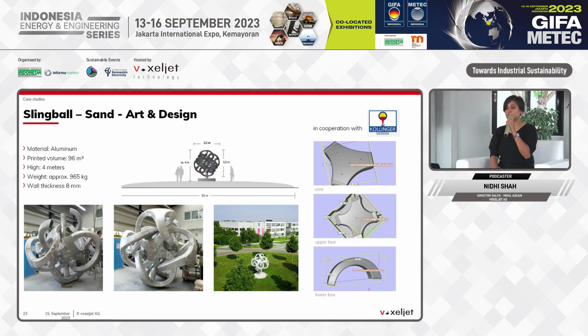This is one of our favorite art projects. It's a sling ball which has a total print volume of about 96 cubic meters, a height of 4 meters. The mold was 3D printed in sand and the casting is in aluminum. The weight is a little less than 1 ton, and wall thickness is just 8 millimeters throughout the casting.